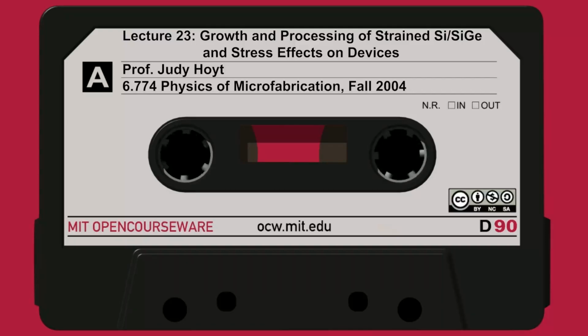So if you're growing at high temperature, or you're annealing at high temperature, if you're at 20%, the equilibrium critical thickness for silicon germanium is about 120 angstroms, 110 angstroms, something like that. So it says that if you're growing at high temperature and you grow above about 120 angstroms of 20% silicon germanium, it'll start to form dislocations at that point. However, if you are growing that same germanium fraction at 550, say, so you're in a very low temperature epitaxial growth, you are kinetically suppressing the formation of dislocations. In fact, the critical thickness is like this curve here, and it's about 700 angstroms.